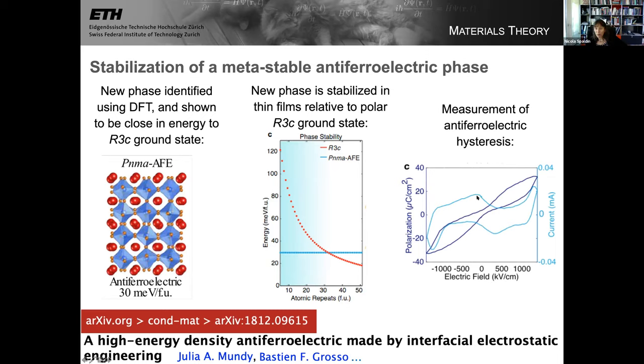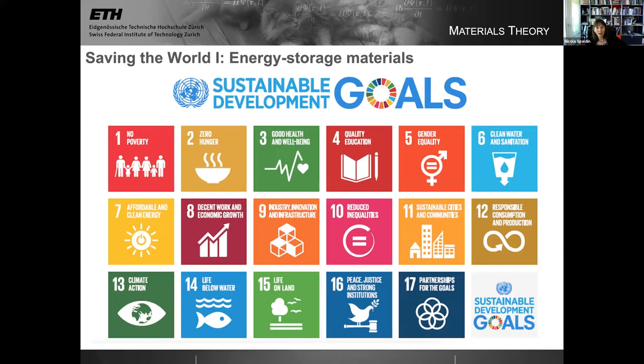It has what's called anti-ferroelectric hysteresis. Look at the blue lines here. So in the absence of any electric field, the measured polarization is zero. But when you apply an electric field, it switches to a polar state. You take the field away, it switches back to this non-polar state and again in the other direction. And these anti-ferroelectric materials are very important because they're candidates for very high energy storage. So this is my first example of a density functional theory calculation being used to engineer materials that might contribute to saving the world in terms of affordable energy and climate action. Because one needs, of course, if one has an alternative source for energy, to have a way to store it, and antiferroelectrics are candidates for this.